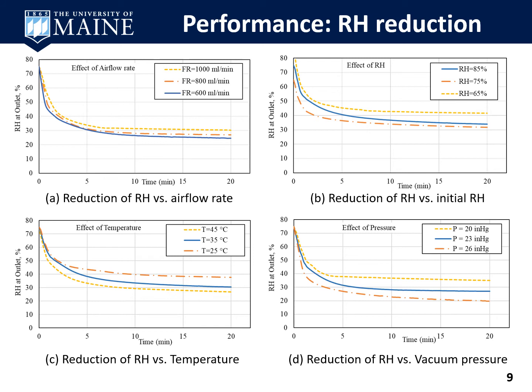We can see the influence of 4 factors: airflow rate, initial relative humidity, temperature of the moist air, and pressure of the vacuum pump on the reduction of relative humidity of the air. We found the relative humidity of the air can be decreased in the first few minutes and then leveled off, and the moisture removal efficiency is in the range of 50% to 80%, depending on the levels of factors used.